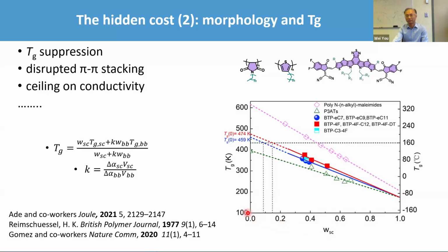If you have no side chain, your conjugated polymer is actually not that bad. You can have a glass transition temperature over like 150 degrees C, which is very robust. Very often for high temperature applications, you possibly want to have Tg as high as you can, like 150, 200 degrees C. Polyimide is really good, for example. But now if you take a look at the green, blue or red curve, once you add the side chain by 40%, 50%, you reduce the glass transition temperature from close to 500 Kelvin down to 350. All of a sudden, you reduce the Tg by over 100 to 150 degrees C.